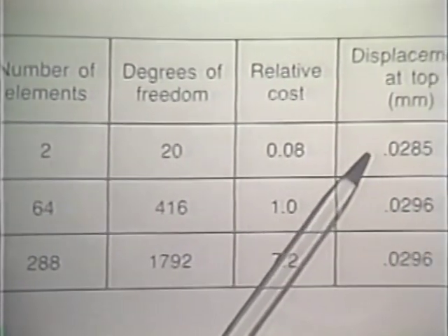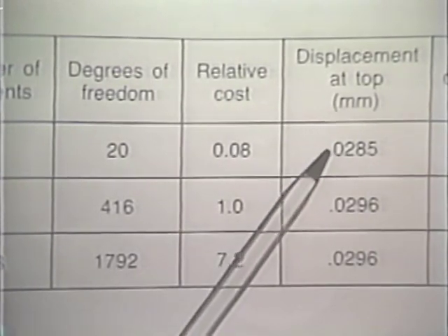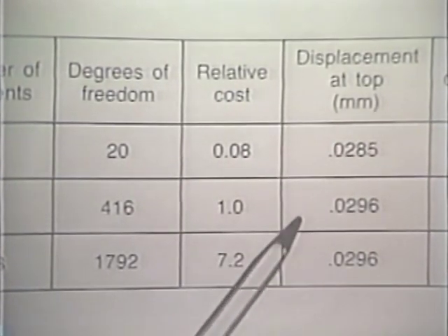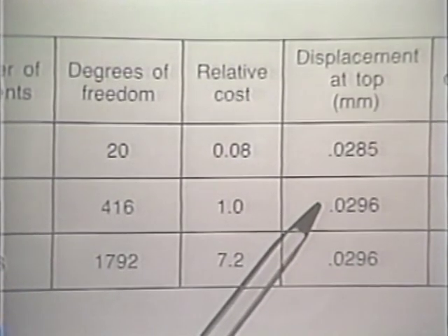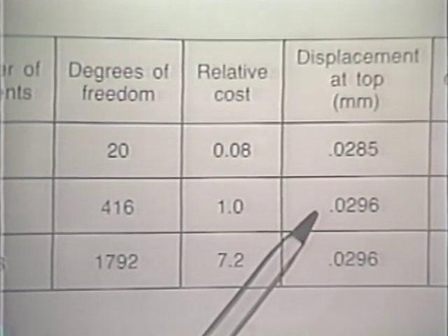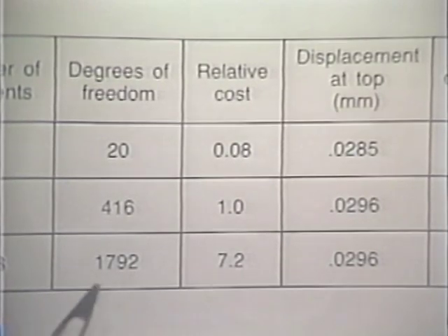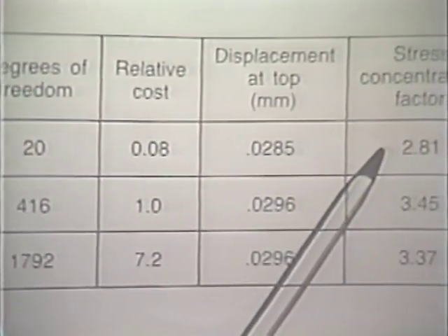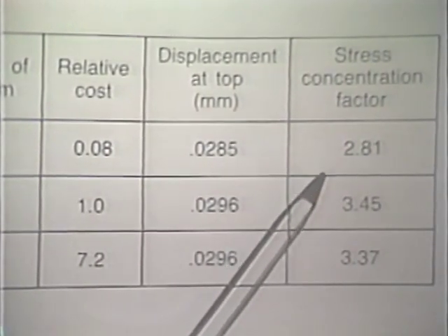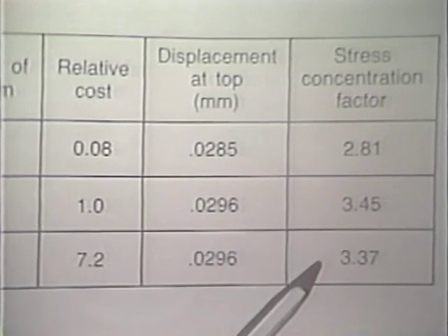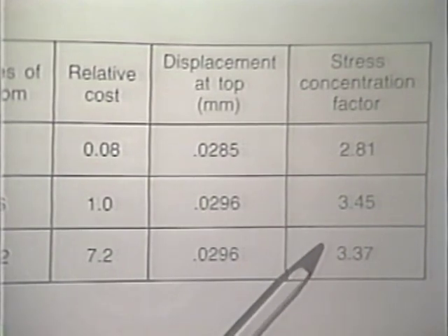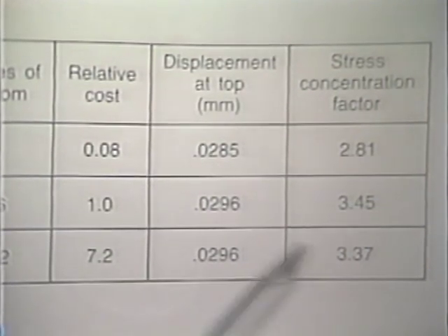The displacement at the top of the plate is given in this column, and we notice that with the 64-element mesh, we really obtain a very good displacement prediction. In fact, there's no change going to a larger number of elements. And the stress concentration factor, interesting enough, increases first and then slightly decreases. Notice this is not an infinite plate, it's a finite plate, and therefore you do not get the value of 3, for example, that you would see for a hole in an infinite plate.